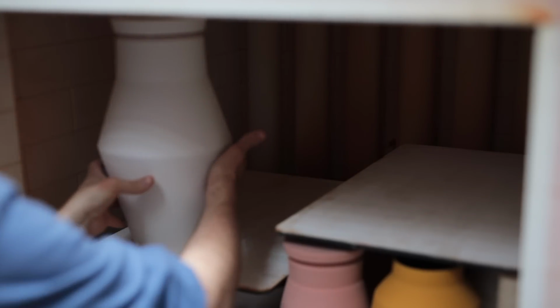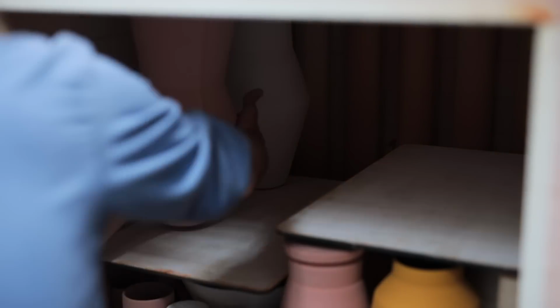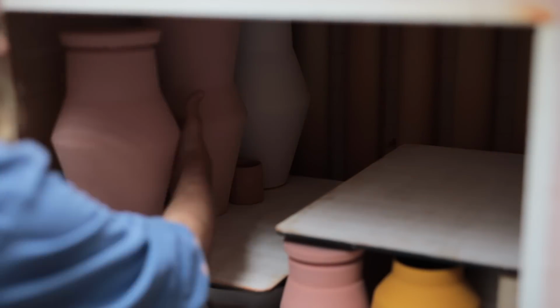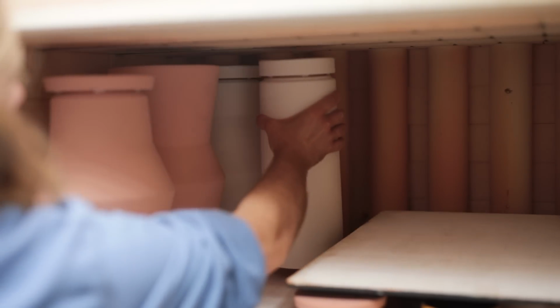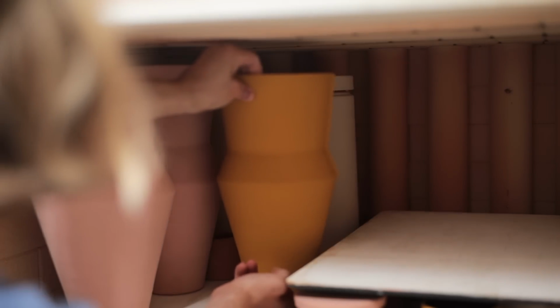I'll be placing both of these jars on the uppermost shelf. This is typically where it gets hottest, and as a result the glaze effects can end up looking rather brilliant, although I'm bordering a dangerous line, as at 1300 degrees Celsius, this clay body will begin to slump where I've trimmed it thinly. And although the pots look rather large and fill the space nicely at this stage, once fired and fully shrunk, there'll be a lot of space around them.